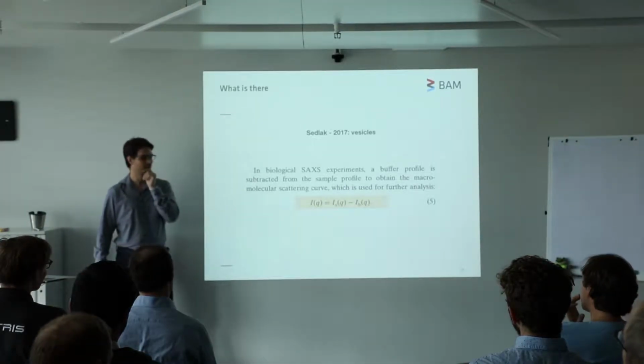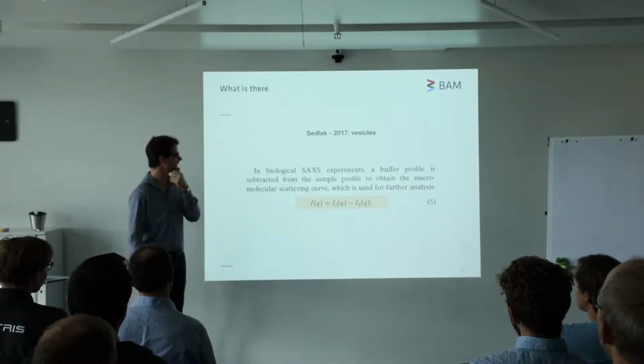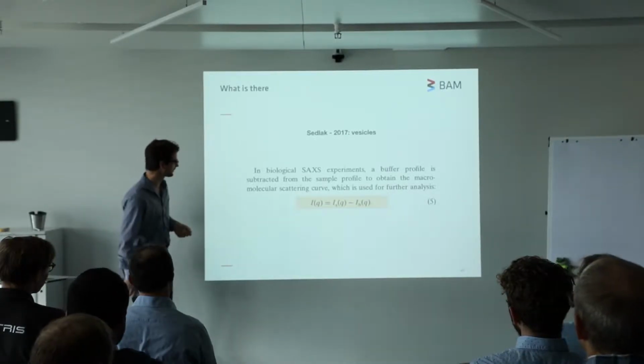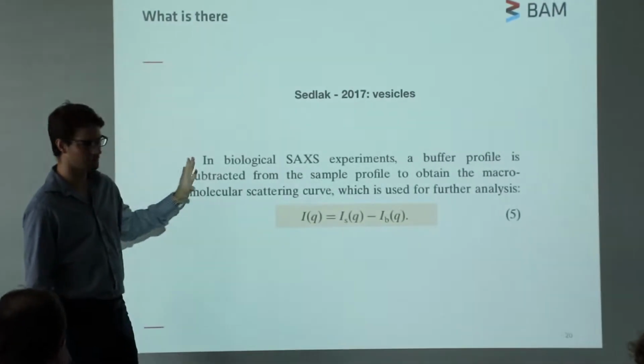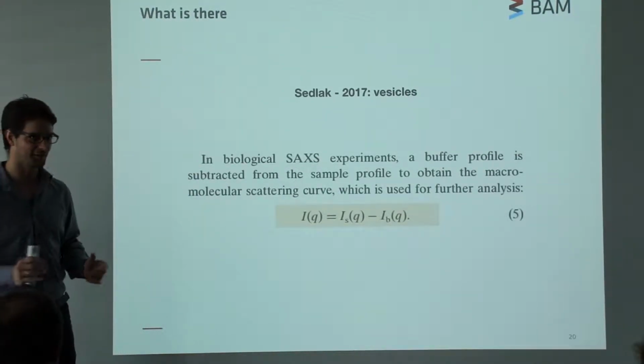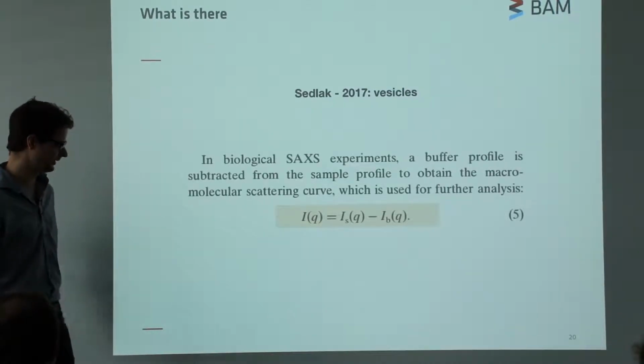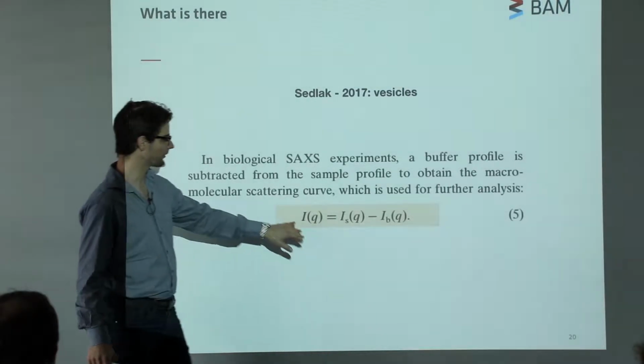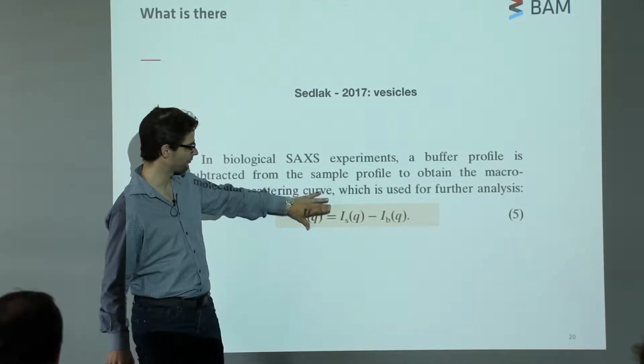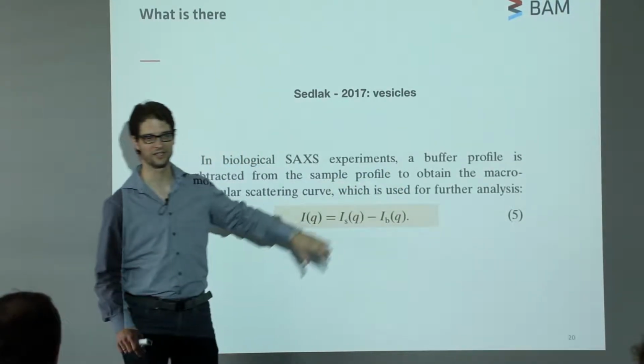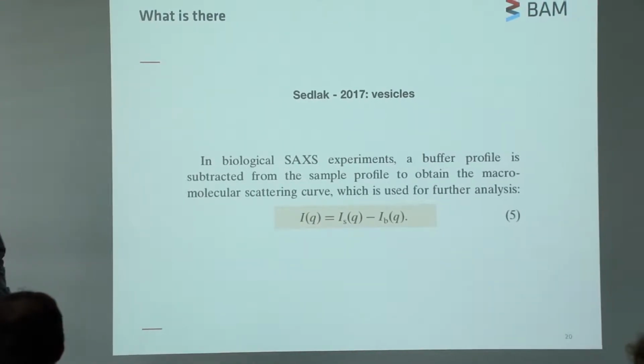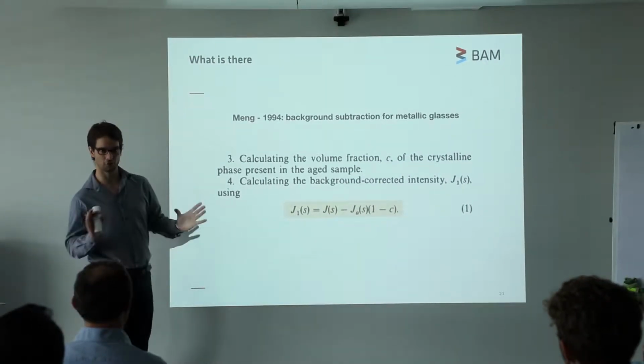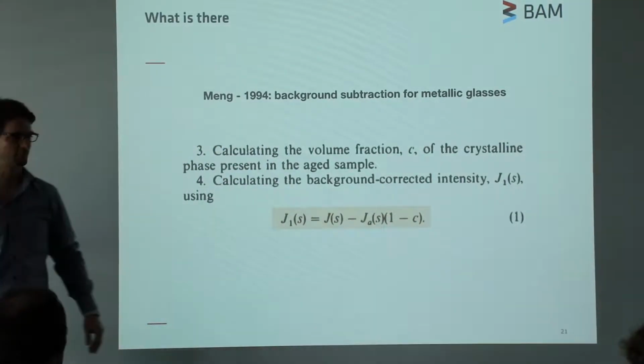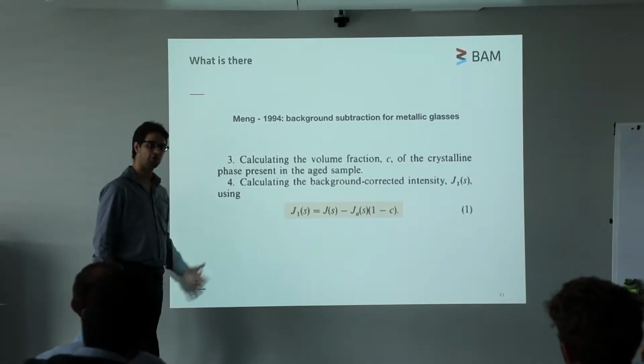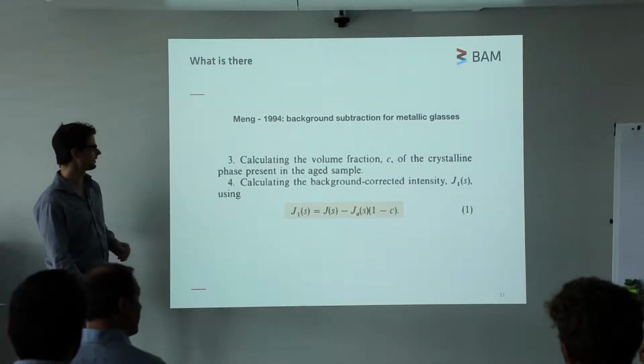In the library for data corrections, you will find a very wide spectrum of information on data corrections. And this is just a cross-section from my library. I didn't take particular attention to lift out anything specific. Here you can see, okay, you can get corrected data by subtracting a background from your sample, and you're done. There is this one, which is almost the same, except that they take a volume fraction of the analyte into account. That's already a step better. And then you look at the neutron scatterers, and of course they did everything better earlier.